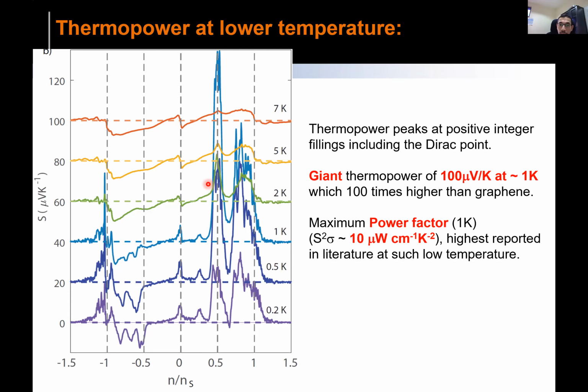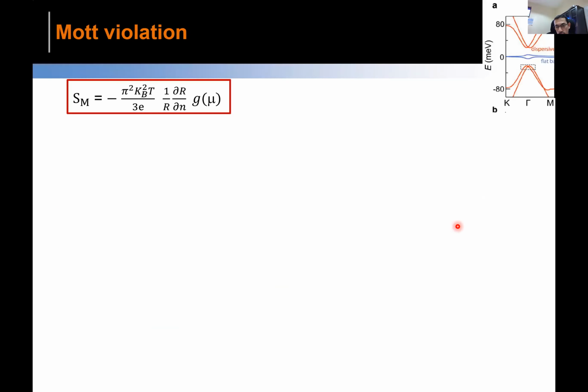But in the flat band around this integer filling, there is a large value, close to 100 microvolt per Kelvin, which is 100 times or even more than graphene at this temperature. If you compare the power factor, this is actually two orders of magnitude higher than any material that exists at such a low temperature.